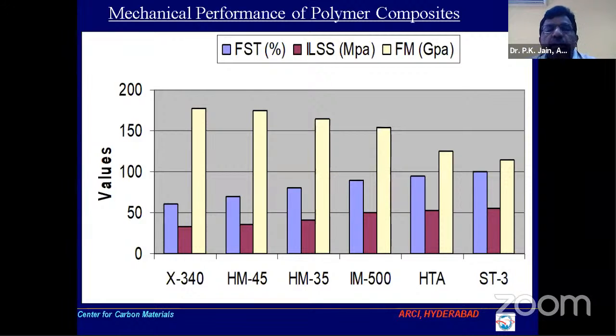So this is the mechanical performance of the polymer composite. When it is a polymer composite, you can see very interestingly that the strength, in the blue bar, is lower for the composite from the low strength fiber as compared to the high strength fiber. The strength of the fiber is directly translated into the composite: where the strength of the fiber was low, the composite also performed low.